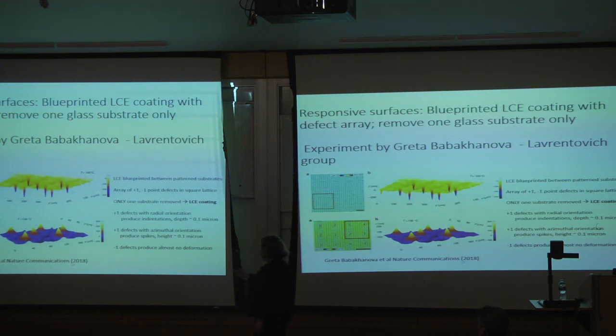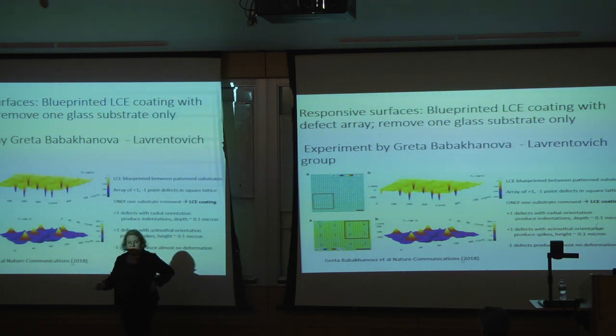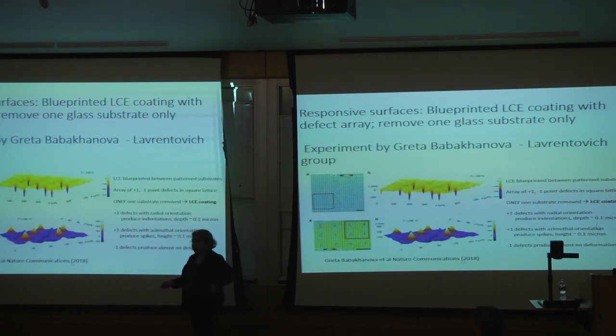So this work was done by Greta Babakhanova, who is an experimental graduate student from Oleg Lavrentovich's group at Kent State. And she actually went to Eindhoven and learned from the Broer group how to prepare these materials. So what she did is she used patterned substrates. The substrates were patterned with the technique developed by another Kent State faculty member named Qi-Huo Wei, where he uses light to pattern the substrates, and we have arrays of topological defects. So she puts the same pattern on the top and bottom surfaces, puts the material inside, forms it, and then takes one piece of glass away.